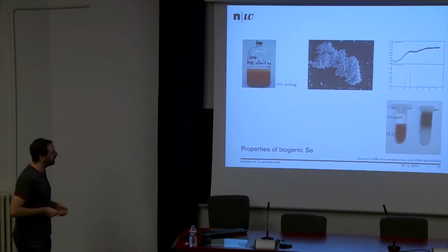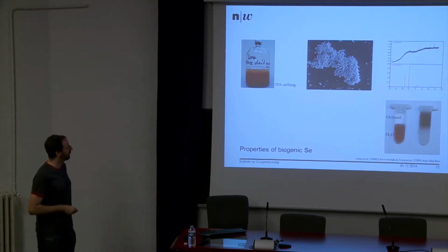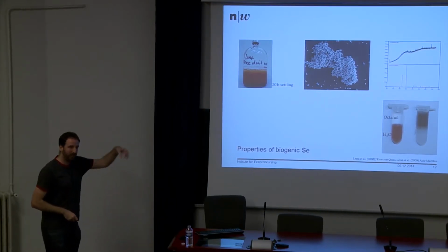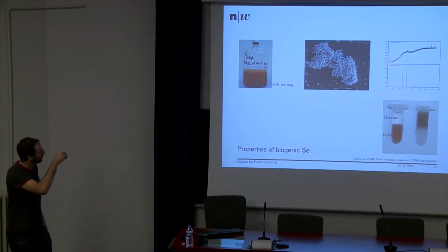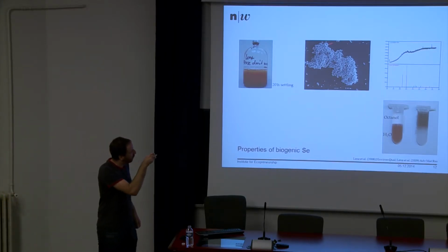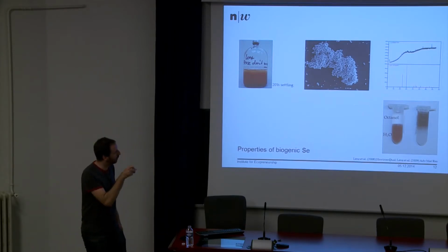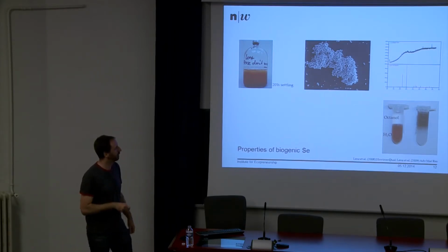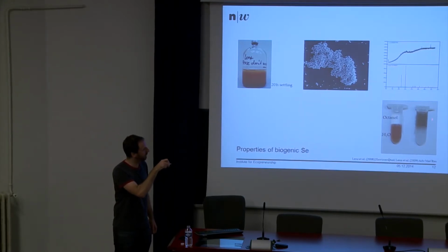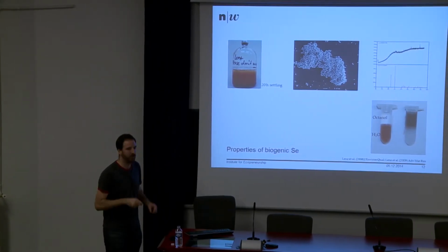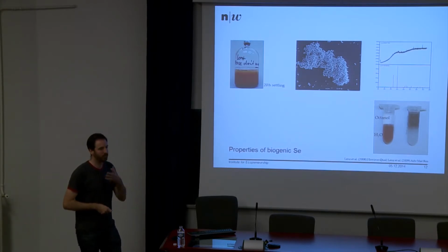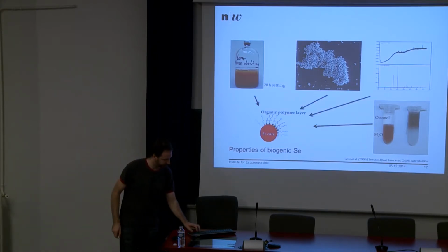So then we were intrigued a little bit by these properties of biogenic selenium. So you see, of course, Lenz, please don't move. When you let the bottle stand, even after 20 hours, you just see a little bit of clarification, but basically they don't settle. We have this nanoparticulate size. We have amorphous particles, or non-diffracting particles. And when you do a very simple octanol-water coefficient experiment, this is chemically synthesized selenium, this is biogenic selenium, you see very, very different properties between this mineral and chemically synthesized selenium.